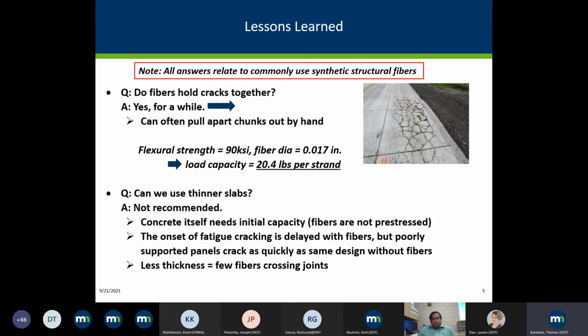Manik alluded to the fact, can we use thinner slabs? I would agree that we're not there. The concrete itself needs to have that initial capacity because these are not pre-stressed fibers. So the concrete itself has to be able to take the initial load. We have seen, however, that if you have fibers in there, the fatigue cracking can be delayed. So it has more capacity, and that's been proven in the laboratory. And that's really where some of the criteria we get for the residual strength came from. Is the fact that once you put fibers in it, you do have more capacity.